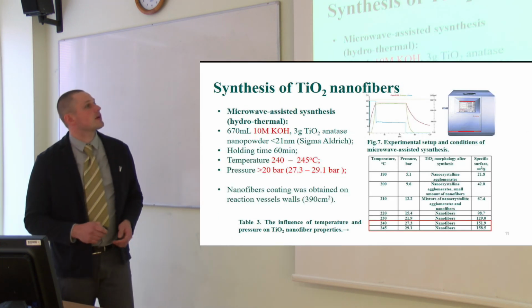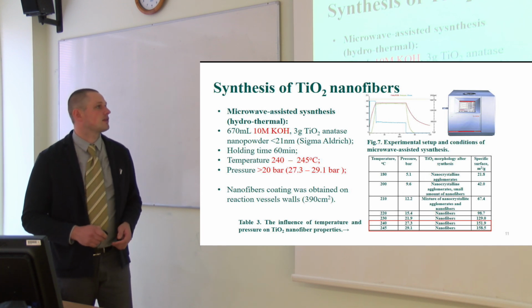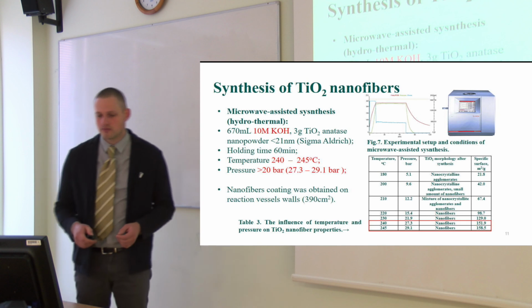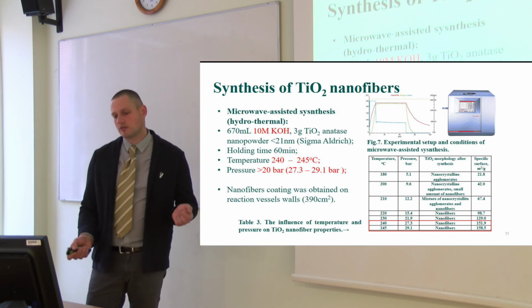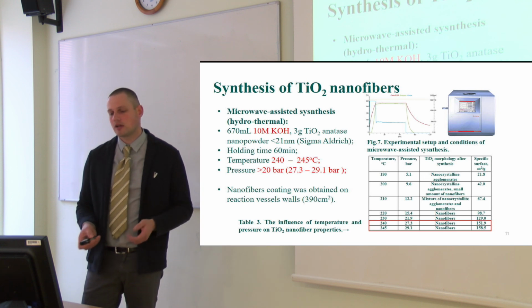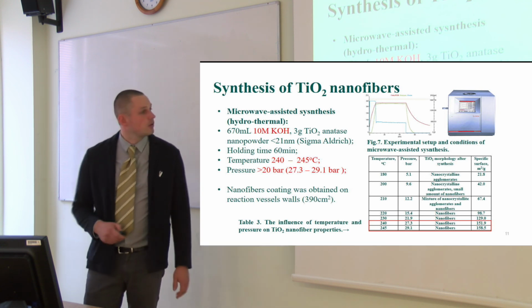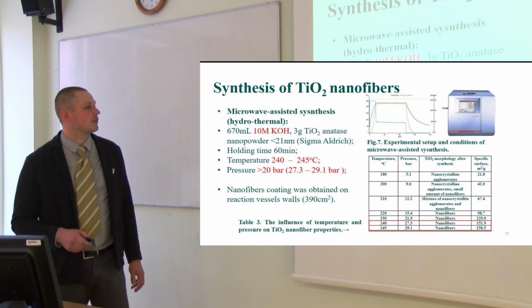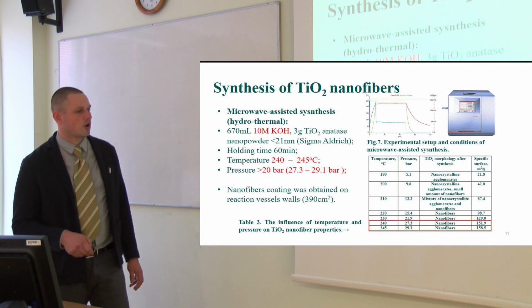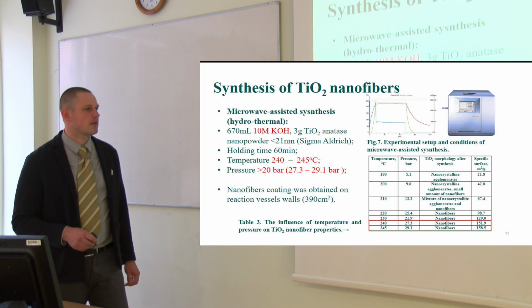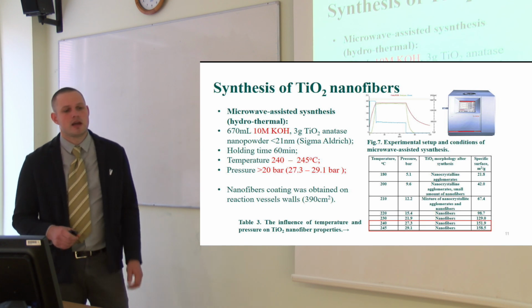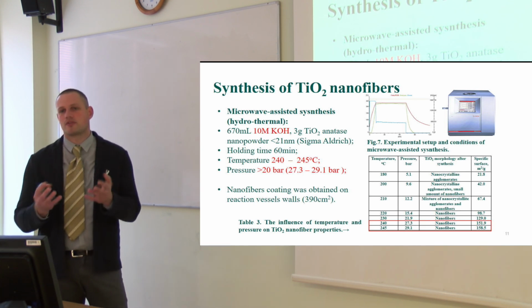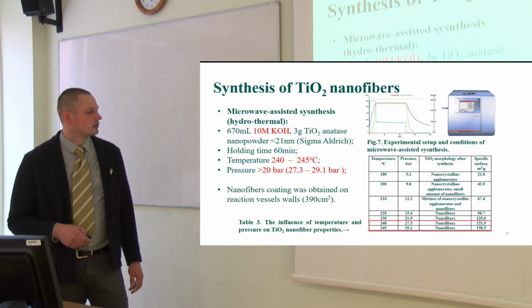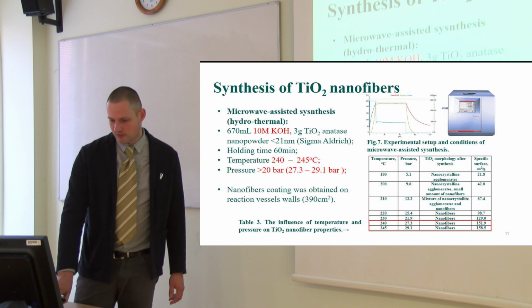So, and the third method was microwave assisted synthesis method. It is some kind of hydrothermal synthesis method. So we use closed volume, we heat it up, and we get a pressure inside this volume. So in our case, the holding time was 1 hour, temperature 240 to 245 degrees. This was the optimum for nanofibers. In such case, we obtain nanofibers with the best quality, and the nanofibers are located on the surface of this reactor chamber. So we can remove them after the process.